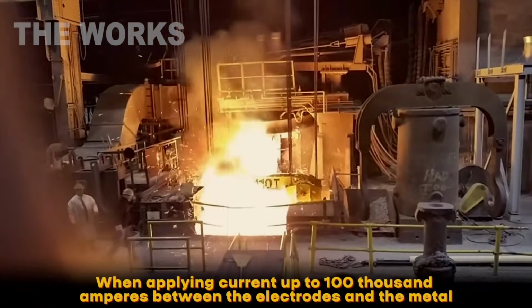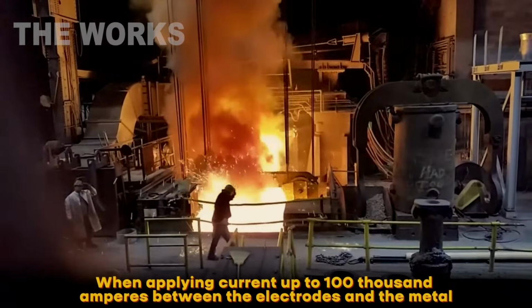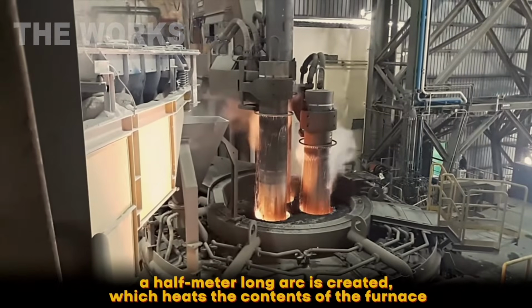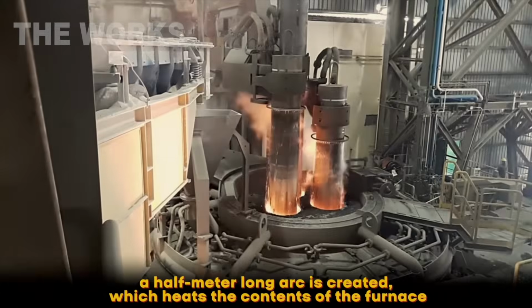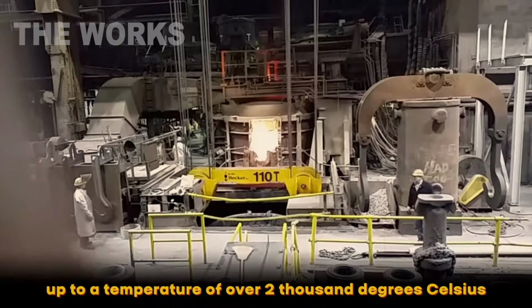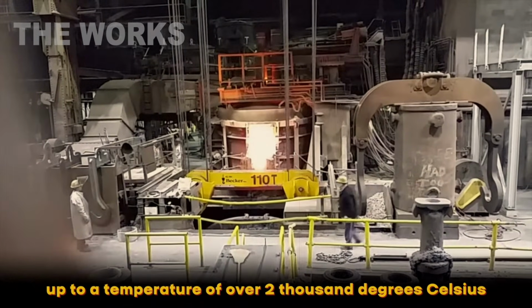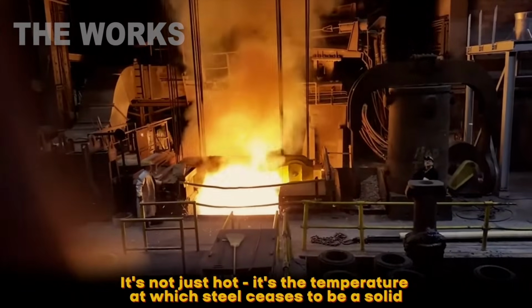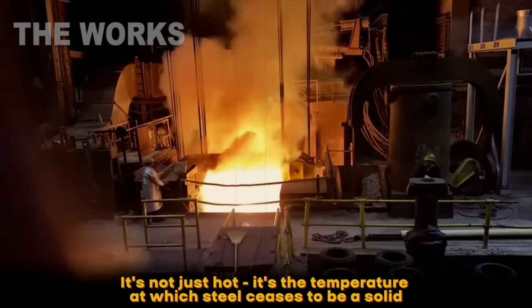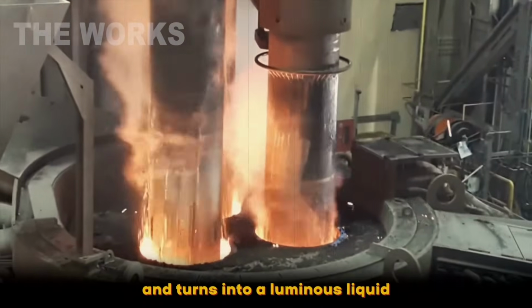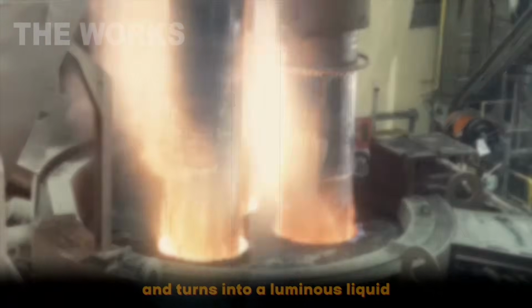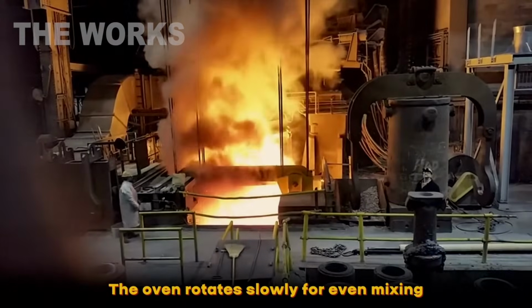When a current of up to 100,000 amps flows between the electrodes and the metal, it creates an arc about 20 inches long that heats the furnace contents to over 3,600 degrees Fahrenheit. This isn't just hot, this is the temperature where steel stops being a solid and transforms into glowing liquid. The furnace slowly rotates for even mixing, while gases are drawn off through powerful filters.